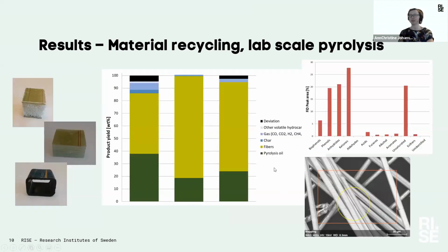And here to the left, you see what the composites look like from the beginning before we put them in the pyrolyzer. Here's a mass balance over the pyrolysis. These composites contain a lot of fibers, and that's why they are not wanted in incinerators, because it produces a lot of ash. But instead, if the fibers can be reused, it's a much better option. And also here we received an oil, and we were able to quantify it and also to characterize it. And also here we found out that the components we received are more or less those that are put into the composites from the beginning.